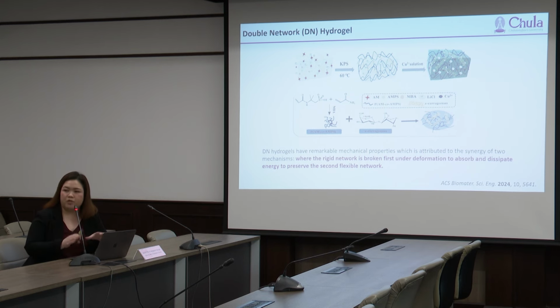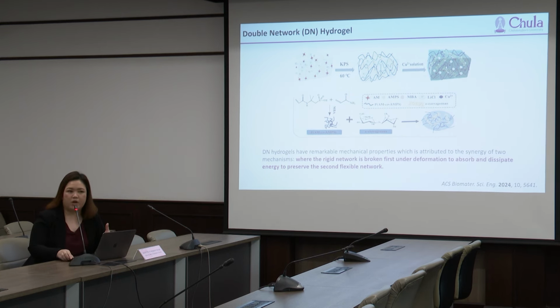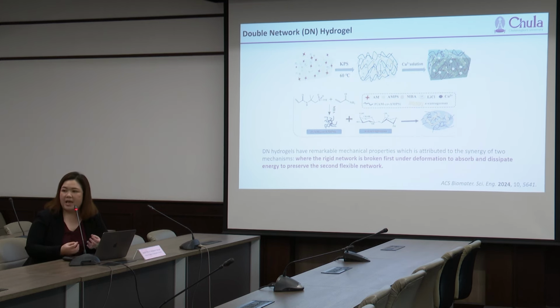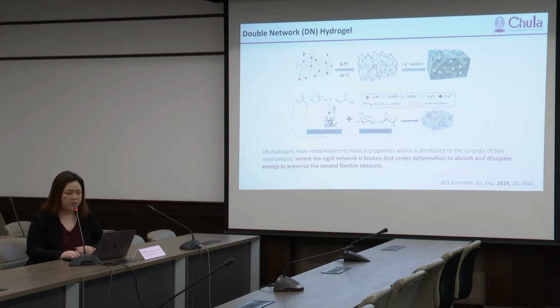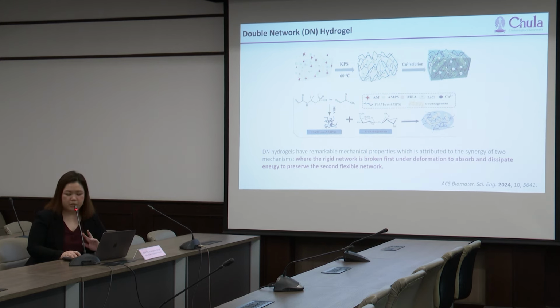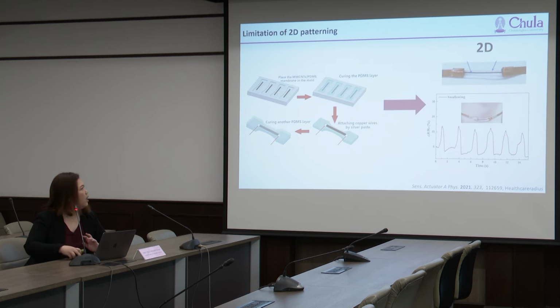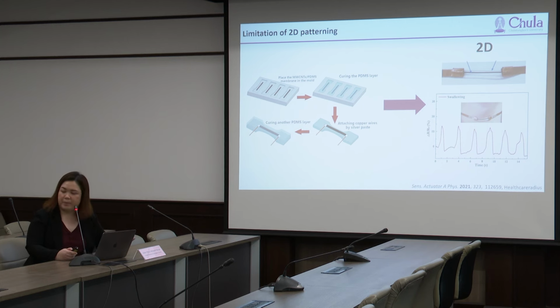When you apply force to the hydrogel, the first network will be broken first under the deformation and absorb and dissipate energy. And then we have the second network that still holds on to the hydrogel network. So when people prepare the double network hydrogel, they usually use the traditional fabrication method, such as molding or the casting method. So this can limit it to 2D patterning.